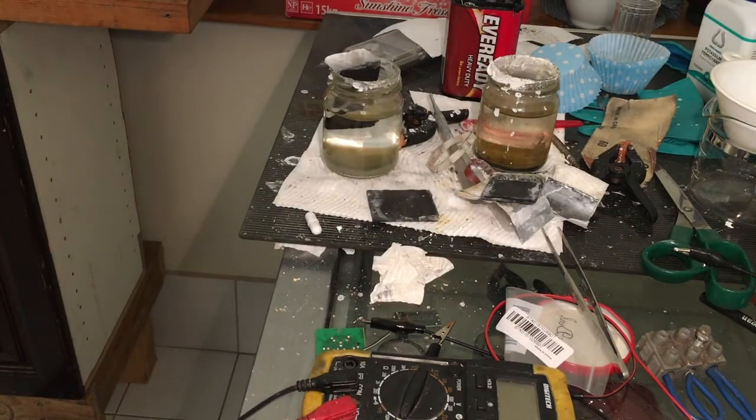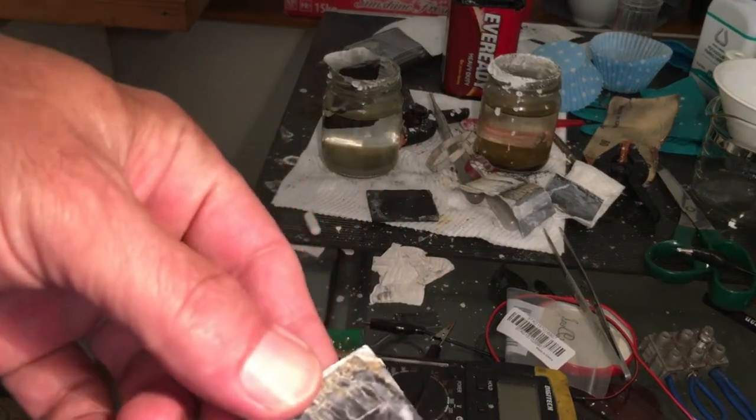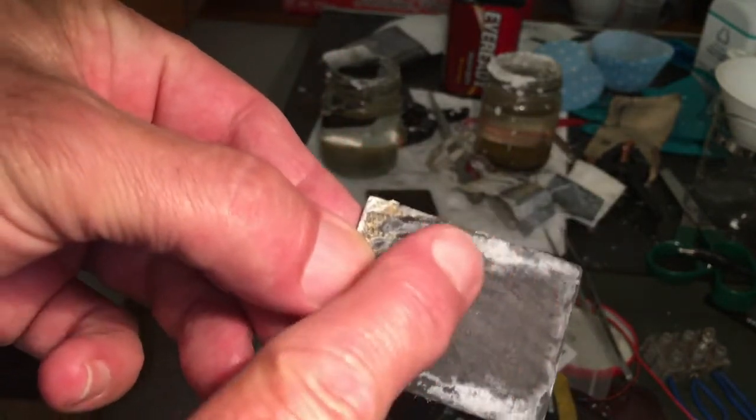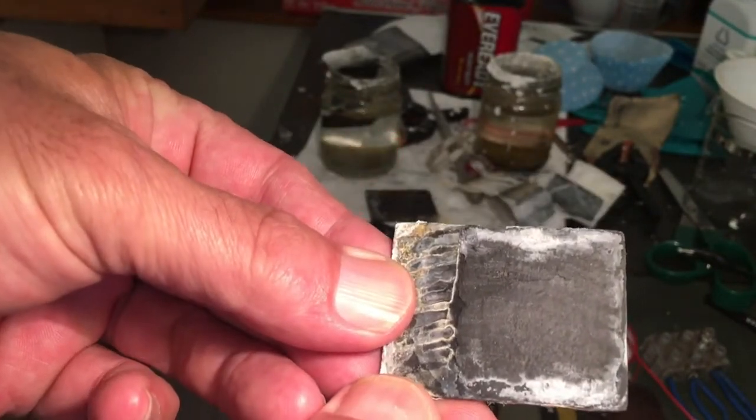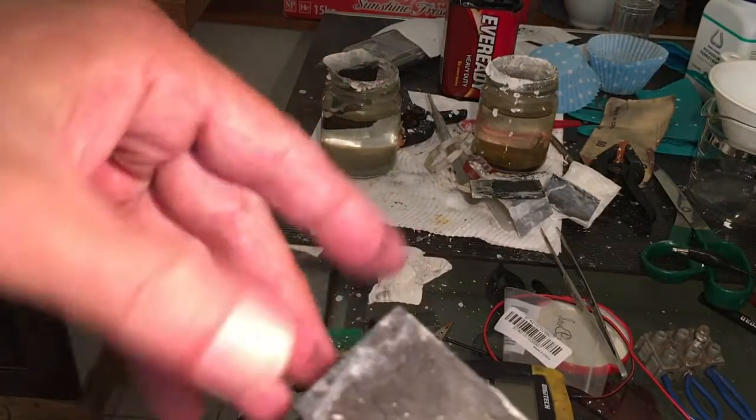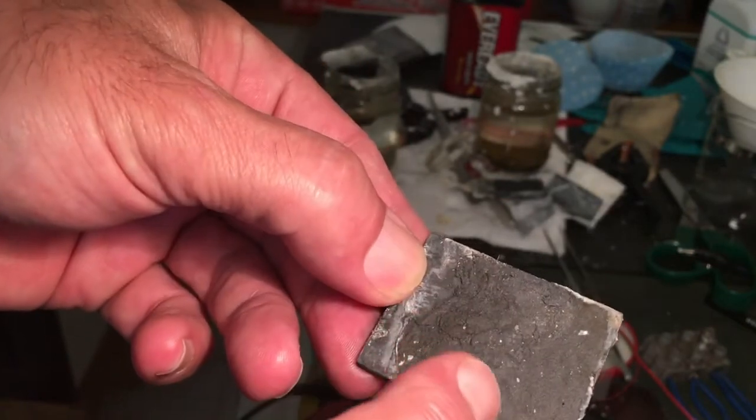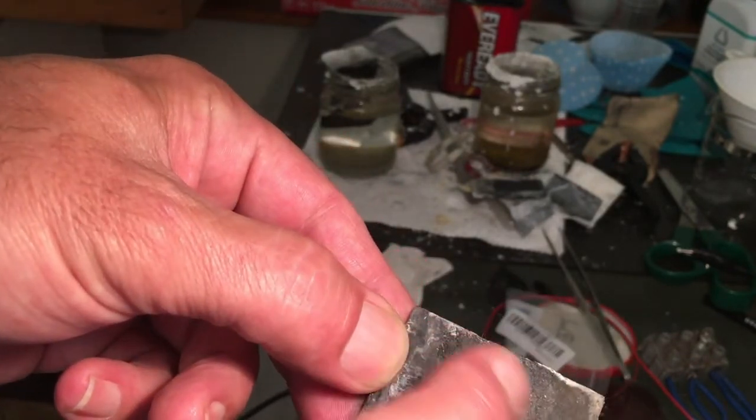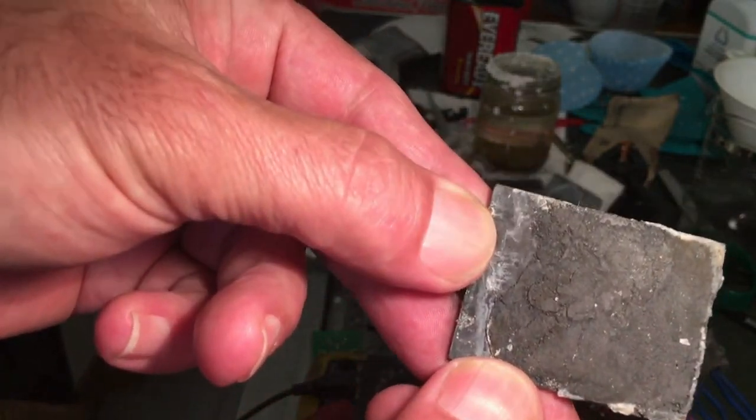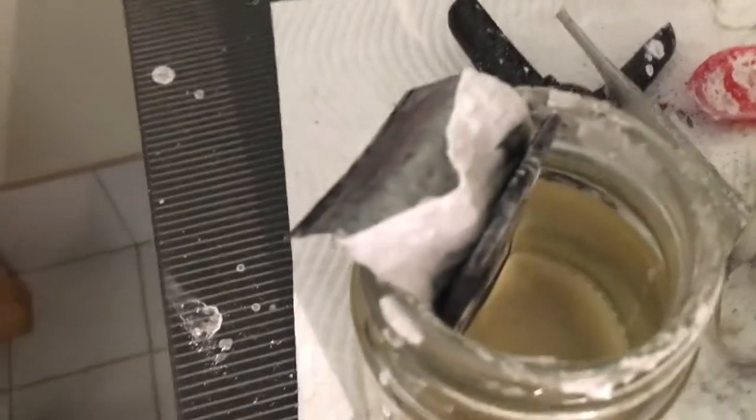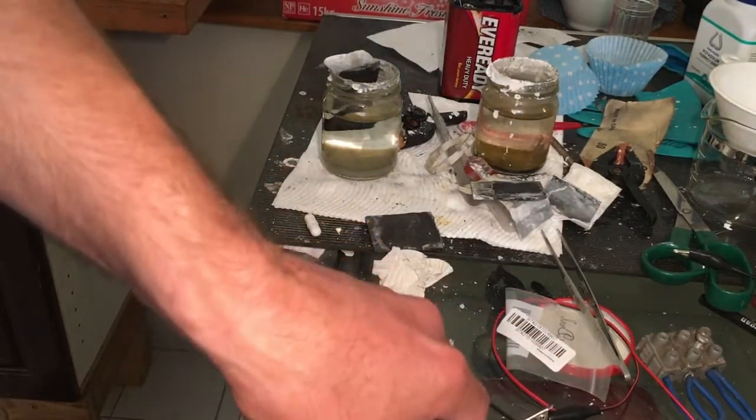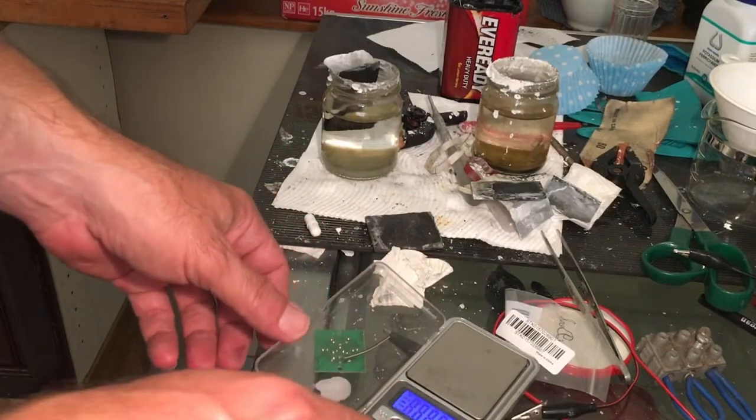I'm back. It's been a couple of days since we've had the test cells running. I've pulled them apart. This was the first one with the contaminated zinc hexacyanoferrate material with the metal stir bar. See the coating is much smoother. This cell actually was still working. But due to the hot day and the cellulose acetate, that was my coating of the other one in the last test which didn't really perform too well. I'm taking it there's something wrong. It's sort of flaking off. And it's a bit rough. And the manganese version of the cell is also a bit rough like that one there. So it's quite hard to use the cellulose acetate membrane. We'll just weigh it up. I'll scrape it off. And we'll see how much actual material we do have on those cells.